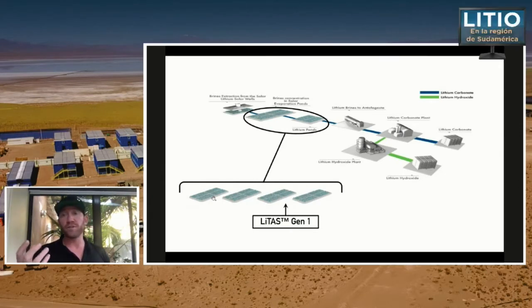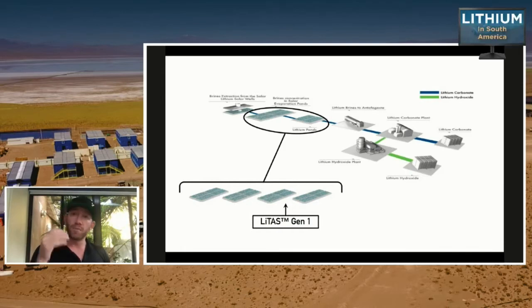The ponds are actually very effective in what they do. The ponds use very little energy because they use the sun. They do a great job in evaporating H2O, and they do a great job of precipitating some of the halite and sylvinite, the sodium chloride and the potassium chloride. And even in the carnallite pond, they do evaporate a lot of the magnesium chloride. It's just when the magnesium starts to precipitate with the lithium that you start seeing the highest lithium losses. So we insert our technology directly before that point.